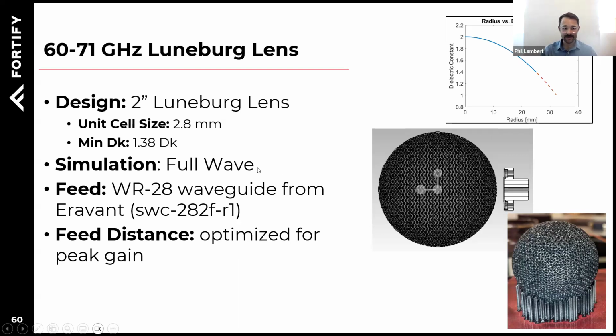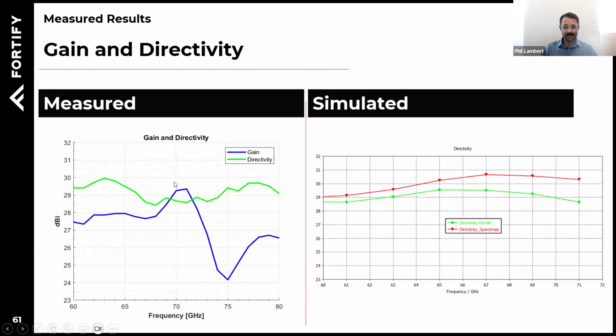We did some full wave simulation on that. We fed that with a WR28 waveguide, and in simulation optimized the feed distance for peak gain. And here are the results. On the left, you're seeing our measured performance where the directivity is in the green, so about just above 29 dBi for this device. And you see the gain drop off pretty significantly above 70 gigahertz. That's correlated to the cutoff frequency for that unit cell at that frequency. So we had expected that there.